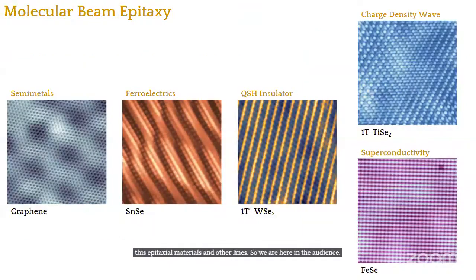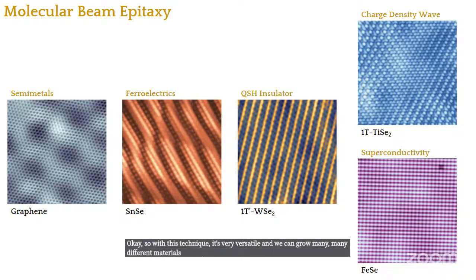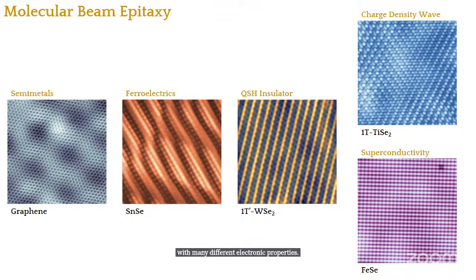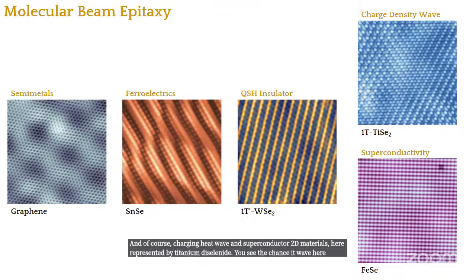Okay, so with this technique, it's very versatile, and we can grow many different materials with many different electronic properties. So here I show you an example. For example, we have grown, and this is one of our favorite, semi-metal, which is graphene. We have grown tin selenide, which is a ferroelectric. We have grown the 1T prime phase of tungsten diselenide, which is a quantum spin Hall insulator material. And of course, charge density wave and superconductor 2D materials, here represented by titanium diselenide. You see the charge density wave here and the superconductivity. This is a monolayer of iron selenide, okay?